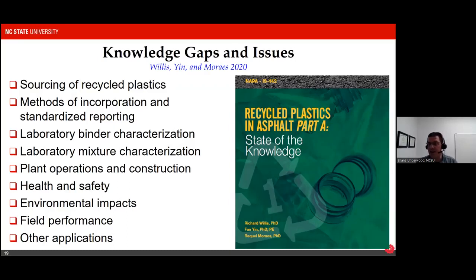We don't have standards to describe the specific gravity measurements of recycled plastics. There are not established standards in the AASHTO or in our transportation agencies to deal with melting temperatures and differentiating between alternative plastic sources and their differences in melting potential. We also don't have established methods in the transportation community to deal with ash content of post-industrial recycled plastic versus post-consumer recycled plastic. So there's a lot of unknowns in dealing with sourcing of these materials. It's easy for us to say we're going to use a load of recycled low-density polyethylene, but there's a lot of engineering differences between the materials that might collectively be classified as low-density polyethylene.